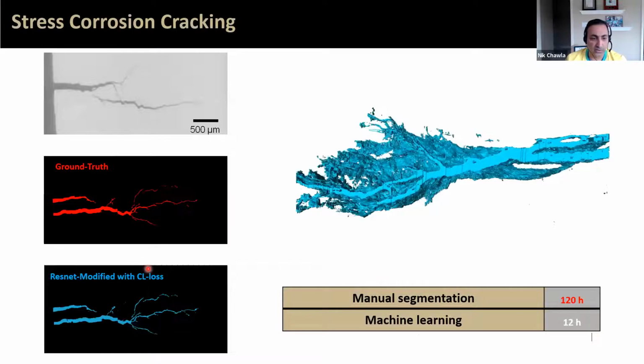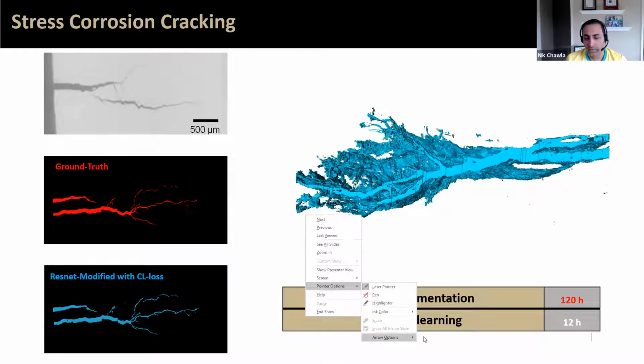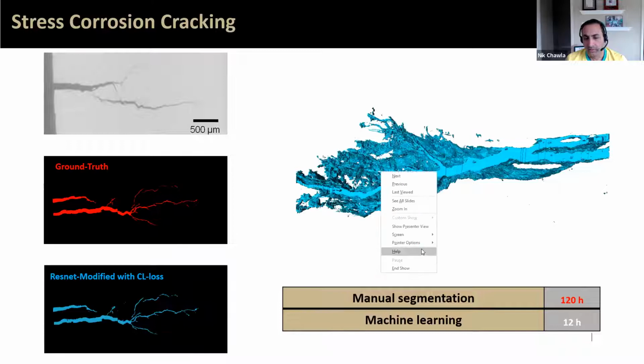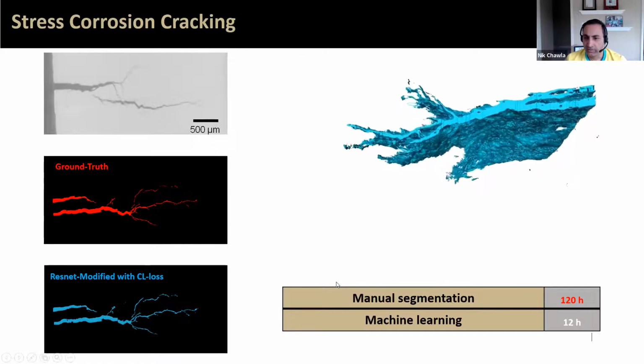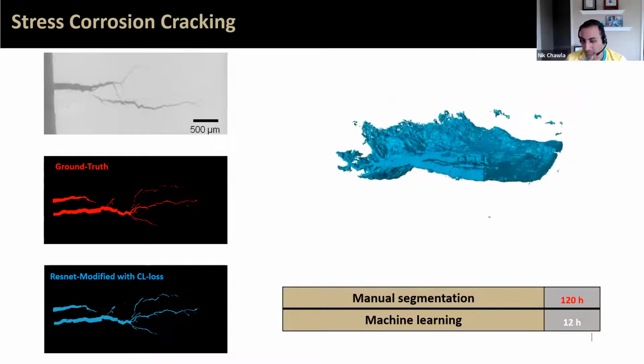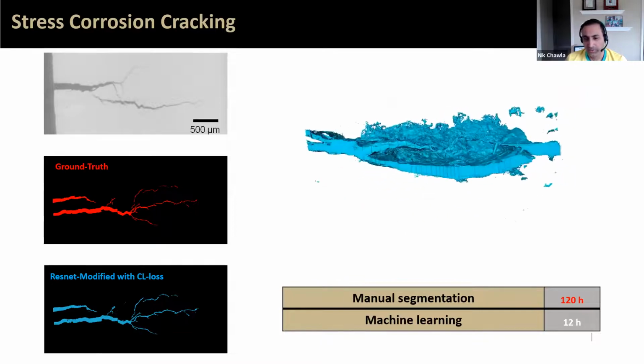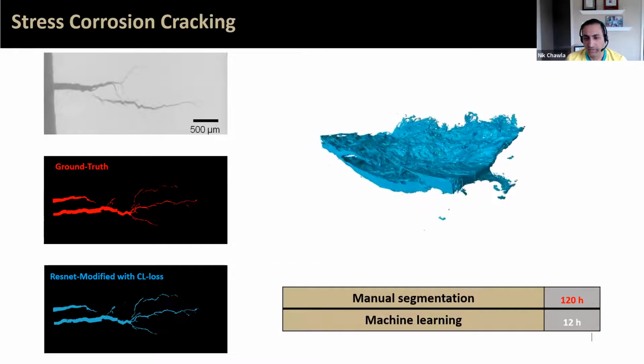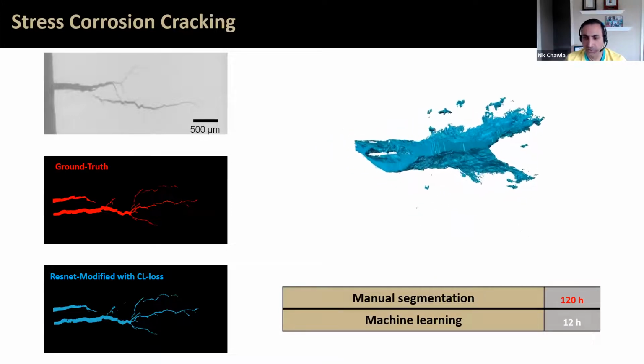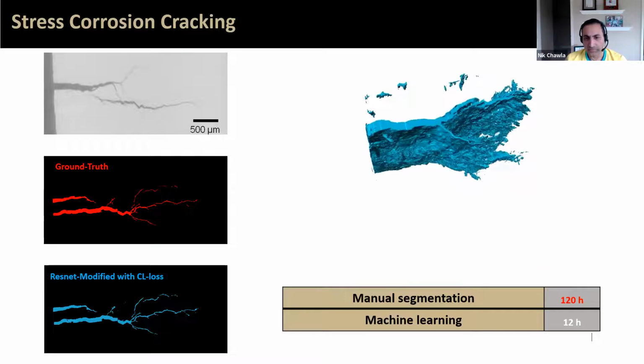Okay, and we've applied this to different types of problems. This is a stress corrosion crack in a steel, and with manual segmentation, this would take 120 hours. With the machine learning, we were able to get this down to about 12 hours. I'll just play you a little animation here of the stress corrosion crack, which is very complex, very tortuous, and really helped us understand the mechanisms and how microstructure was controlling stress corrosion cracking.